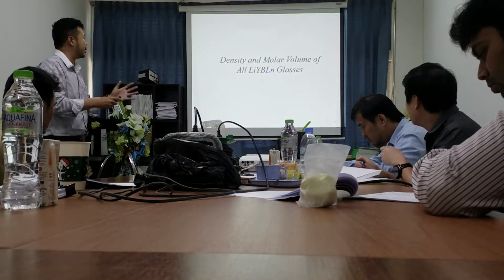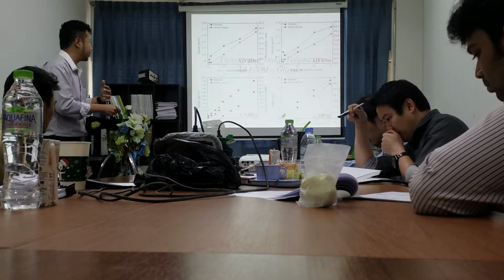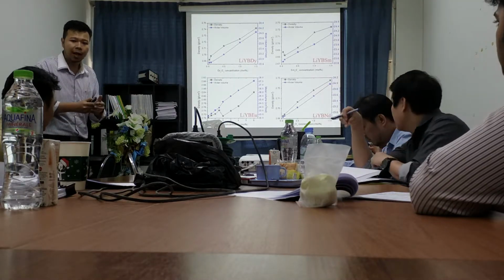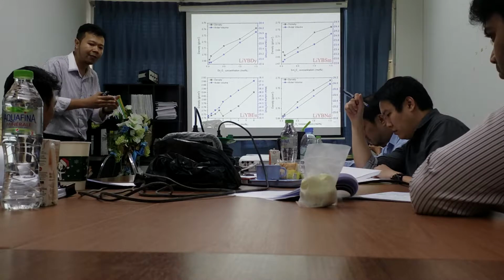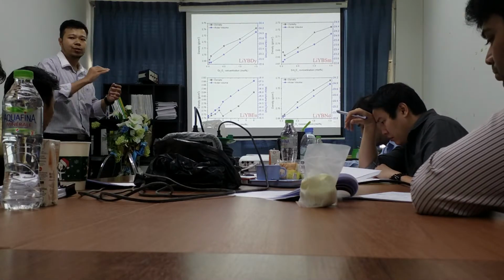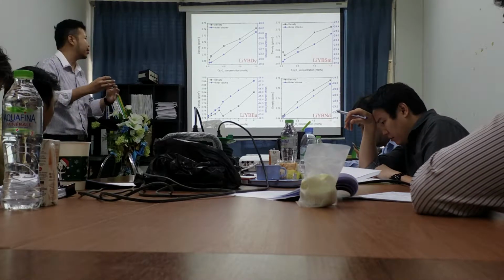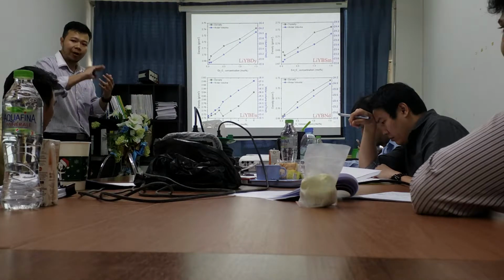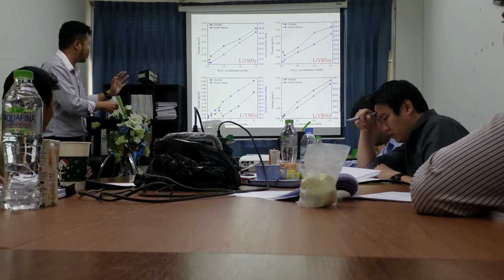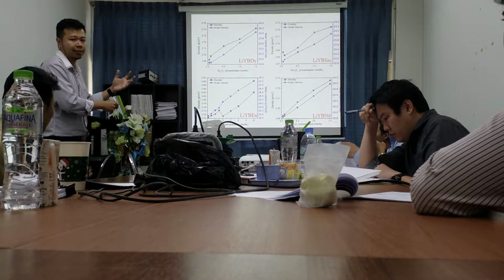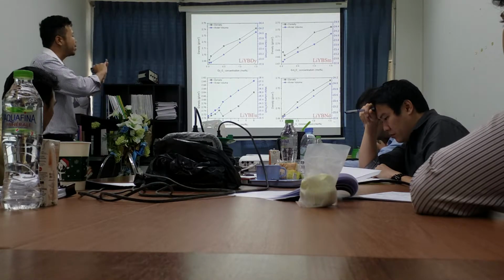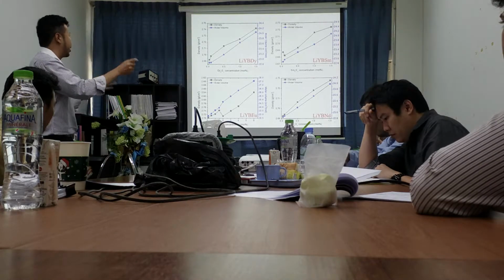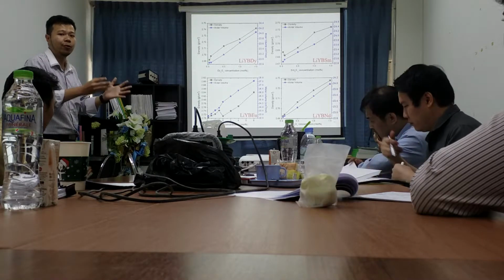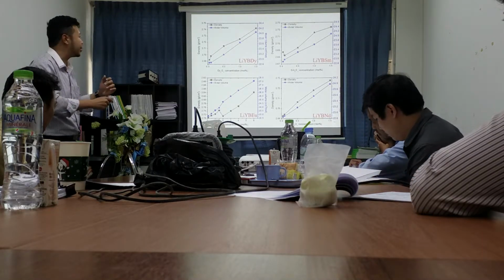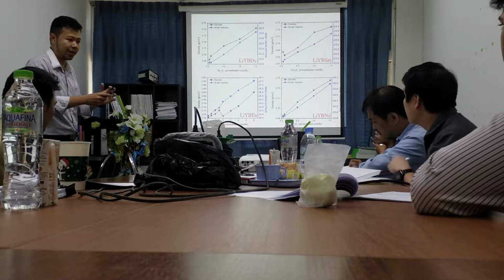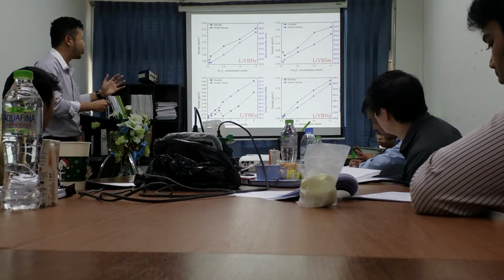Now I move on to the density and molar volume of the glass. These are all the results about the density and molar volume of my glass. They show the same trend. We have some error values in the relation, but if we consider the trend, density and molar volume tend to increase with increasing lanthanide oxide concentration.